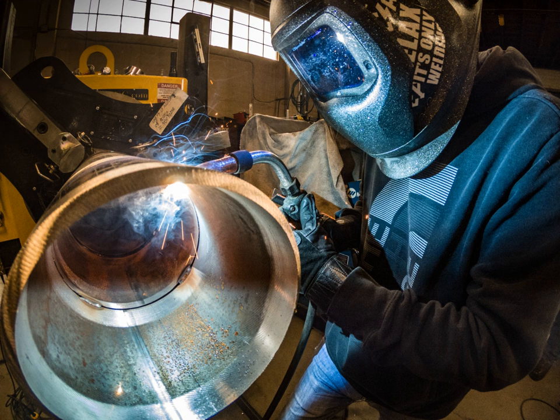Non-consumable electrode processes, such as gas tungsten arc welding, can use either type of direct current, as well as alternating current. However, with direct current, because the electrode only creates the arc and does not provide filler material, a positively charged electrode causes shallow welds, while a negatively charged electrode makes deeper welds. Alternating current rapidly moves between these two, resulting in medium penetration welds. One disadvantage of AC, the fact that the arc must be reignited after every zero crossing, has been addressed with the invention of special power units that produce a square wave pattern instead of the normal sine wave, making rapid zero crossings possible and minimizing the effects of the problem.